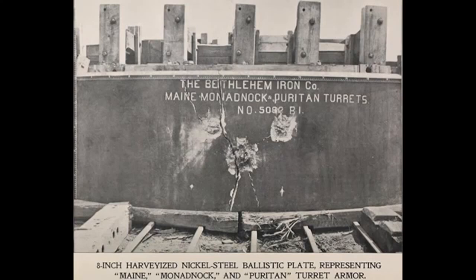Now, this process would give you a steel plate with an integral hardened face and a tougher back. This gave about a 20% greater level of resistance compared to nickel steel on its own. The Harvey process was rapidly adopted the world over, as you could once again drop the thickness of armour for the same protection and thus save weight. Compared to the old iron plate, Harvey steel offered at least 60% greater protection if you took the very best iron compared with the worst standard of manufacturing past Harvey steel. At its best, Harvey steel offered double the protection of the average wrought iron plate that had been in use as little as 10 to 15 years ago.